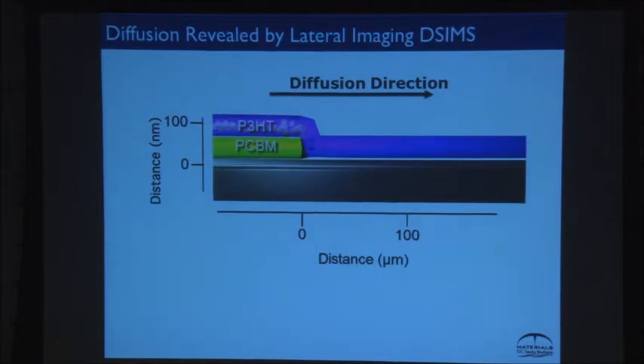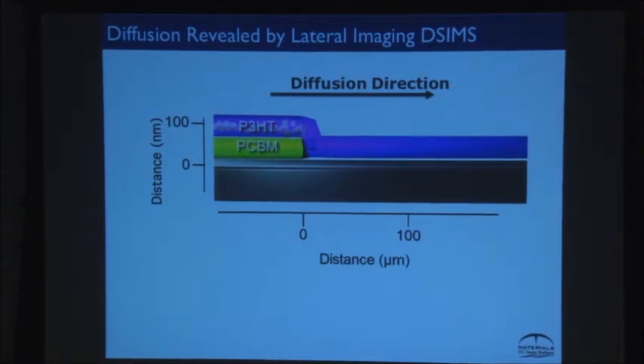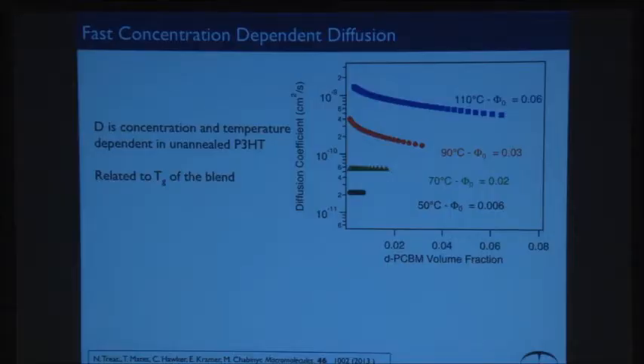So what we found was we needed a nice measurement to back out the diffusion constant. We'd always been measuring SIMS vertically, and so we can't quench fast enough. And so the solution to that is, well, if we can't go fast enough, let's add more distance. So we can do an experiment where we make a bilayer of the fullerene and the polymer and just measure laterally using our SIMS, because we can do imaging. The scale bar is funny here. This is only hundreds of nanometers this way and hundreds of microns the other way. We can actually watch the fullerene diffuse laterally, huge distances.